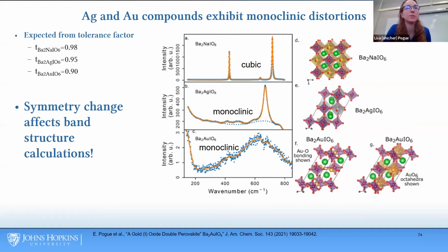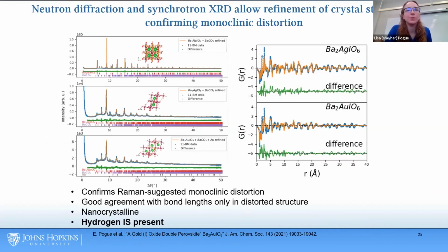This phase, as well as the barium silver periodate, are actually monoclinic variants of the double perovskite structure. This change in symmetry has a strong effect on the eventual band structure calculations. I had done X-ray diffraction and neutron PDF analysis on these materials and found evidence that hydrogen is definitely present in those, which is not too surprising given the hydrothermal synthesis that I used. But for devices, this becomes a problem, which I'll talk about a little bit later.